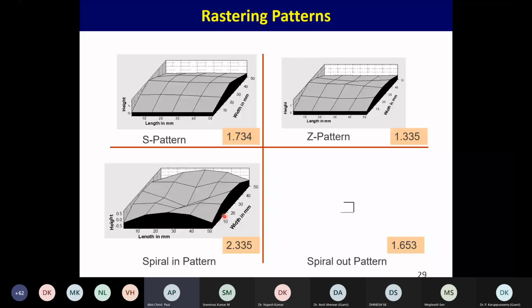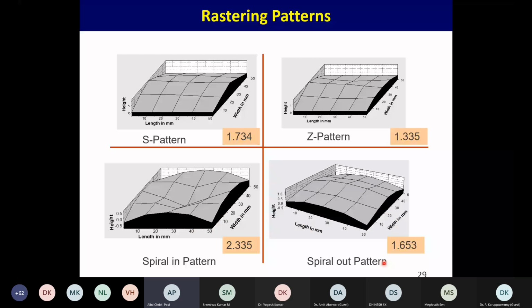So what I want to say is, though it looks obvious and very simple, that things can be resolved very nicely and without any problem, it doesn't happen. Every rastering pattern brings a different distortion to the product, and one has to consider these as a parameter. And I'm saying the Z pattern gives the least distortion in our case because of the similar heating and cooling pattern during the whole process.